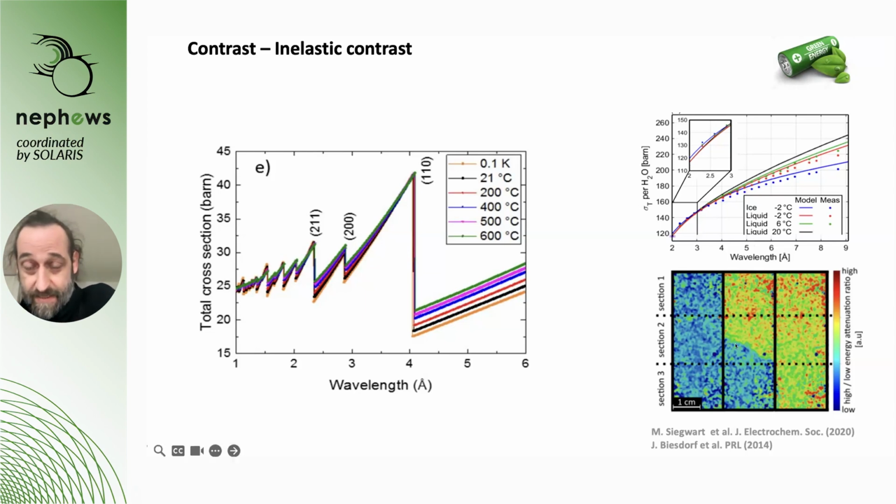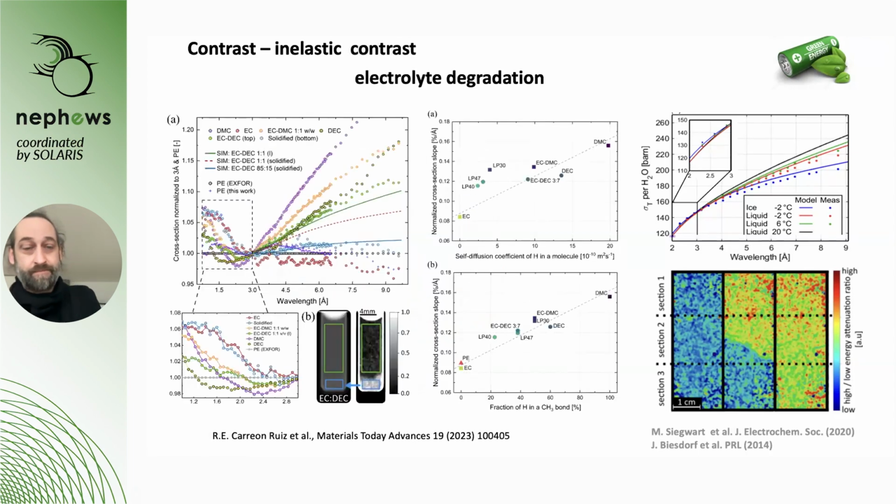So we studied here how freezing of water occurs in fuel cells, and how long this water can also be at minus temperatures but still liquid, so supercooled water. And we can observe these phase changes in the fuel cell due to this inelastic contribution to the attenuation quite in detail and with spatial resolution. So we also see where things happen, when things happen, and how they move through the cell.